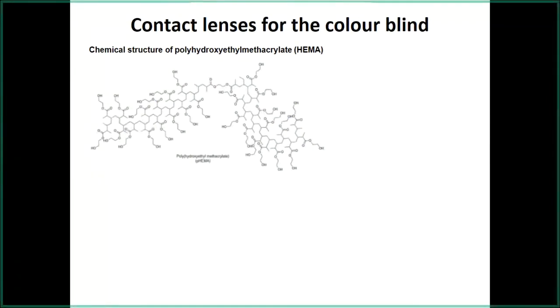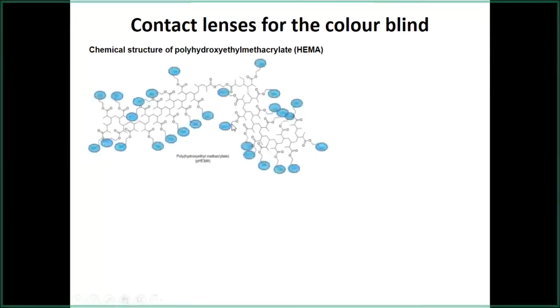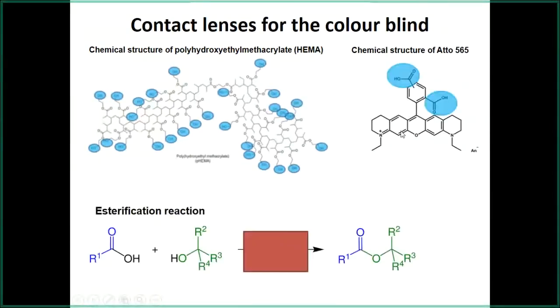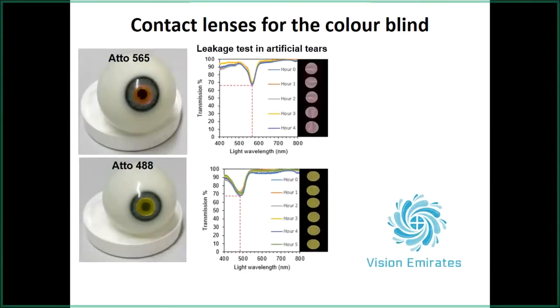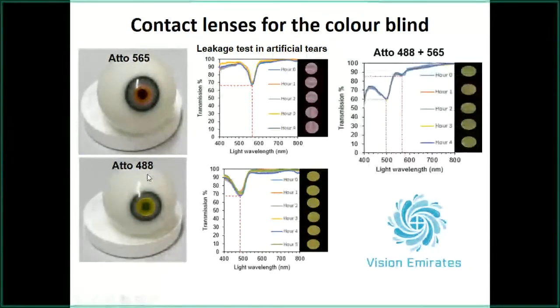Our work ahead has been mostly in getting rid of that leakage issue. So this is a hydrogel, and this was our dye that we were using. After a lot of interaction with the chemists, we came up with a process in which we chemically cross-link them. So the contact lenses we produce now don't have this leakage issue. As you can see over here, the transmission is not decreasing. We have made contact lenses for different optical windows for different CVD types, and we are also making contact lenses which overlap, so they can provide filtering for more than one band.